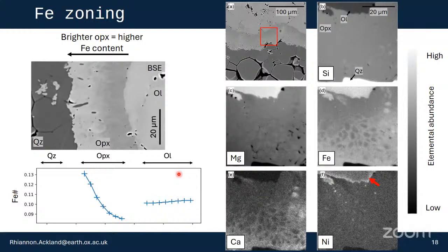Another interesting feature of the experimental results is the distribution of iron within the orthopyroxene rims. You might expect that because olivine obviously has much more iron than quartz, the orthopyroxene would show a diffusion profile with high iron adjacent to olivine and low iron adjacent to quartz. However, this is exactly the opposite.